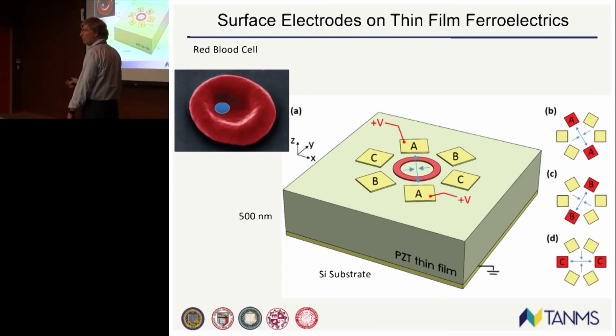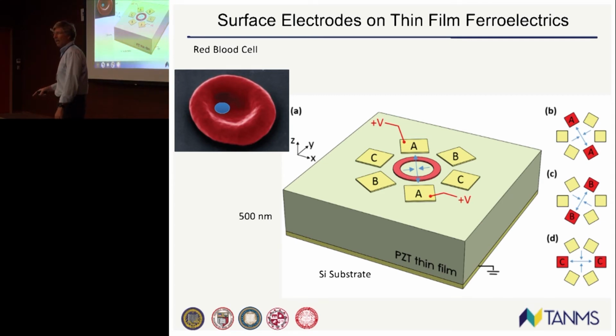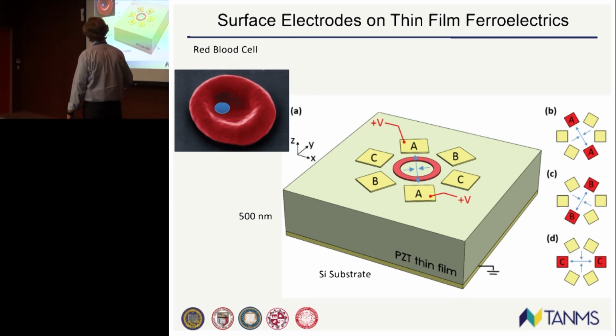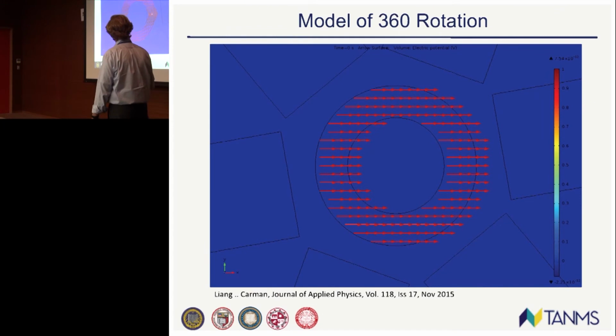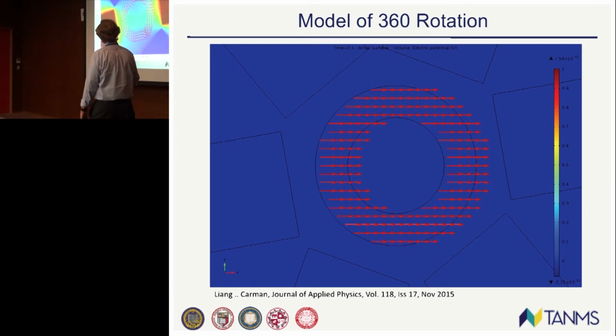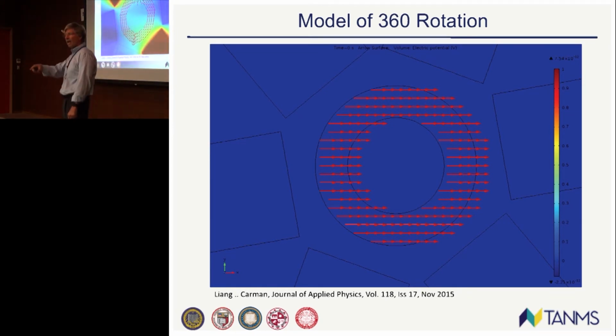PZT thin film again, right? We want it efficient. It's still on a silicon clamp substrate. But you see these A, B, C? Those are electrodes now. And they're spaced every 60 degrees so that we can actually develop a clocking mechanism. So if we go in and do this modeling, we get our onion state. We apply an electric field here. It rotates over about 45 degrees. We take the electric field off. This is stable because there's no shape anisotropy. And then we hit it with another electric field on these two, and we get that system going an entire 360 degrees around. So that's really cool.